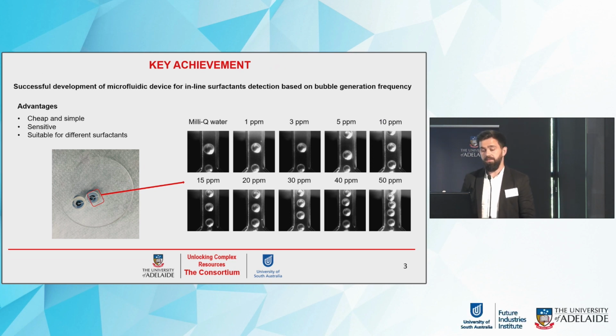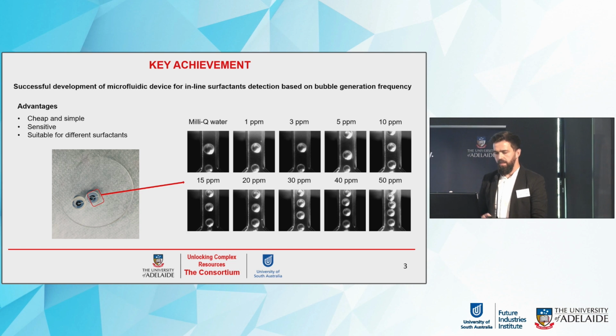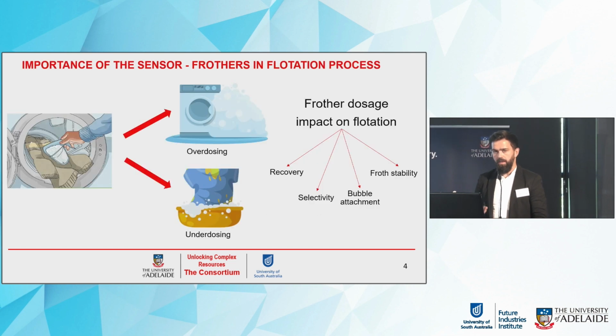And the key advantages of these sensors are that it's quite cheap and simple because we just need a high-speed camera to count bubbles. It's very sensitive, as even a small amount of frothers will affect significantly the bubbles inside of the microfluidic channels. And it can be used for various surfactants having completely different adsorption properties. And why is this important? Because currently there are no methods available for inline measurement of flotation frothers.